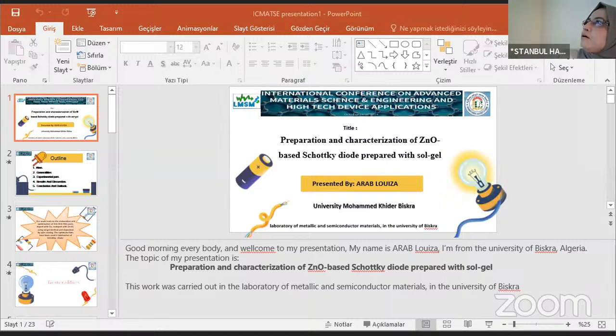We notice that all samples present the hexagonal wurtzite structure of ZnO. This indicates that doping with gallium, aluminium, and indium doesn't fundamentally change the structure of zinc oxide. We can say that we have a solid solution. Peaks marked with an asterisk are peaks of the Al2O3 substrate. We have this in the second figure and the third figure, all these peaks are attributed to the substrate.